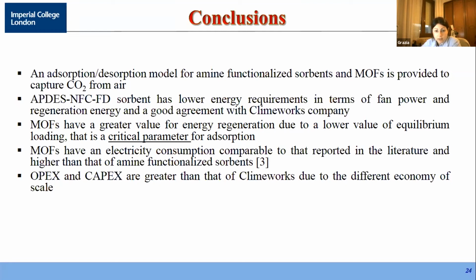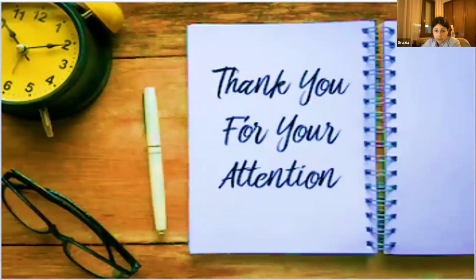We found that MOF have higher values for energy regeneration due to a lower value of equilibrium loading, which can be considered a critical parameter for the adsorption. Also, this sorbent has an electricity consumption higher than amine-functionalized sorbent, but similar to those reported in the literature. And we have costs that are higher than Climeworks due to the different economy of scale. Here are the references, and thanks for your attention.